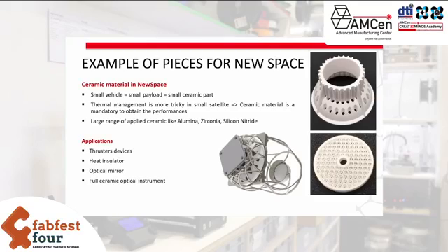You have to keep in mind that optical application is one of the bigger markets for new space, but also structural application, where you use the properties of technical ceramics, such as silicon nitride or alumina, and you can really have a structure which will not be deformed with the difference of temperature in space. So, to explain, when the structure sees the sun, it may go up to several degrees. And when it does not see the sun, it may go down to, let's say, minus 40, 50 degrees. With this gap of temperature, the structure is deforming and the satellite is not working well. And it is not the case with the ceramic parts.